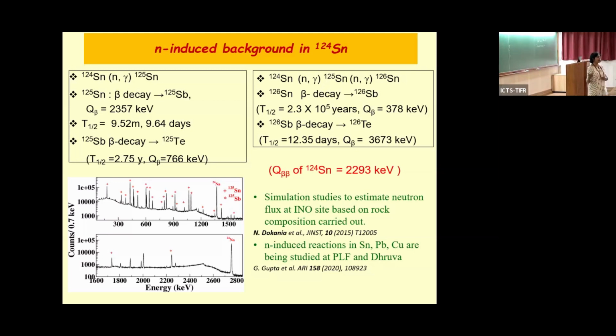So like when we bought the Roman lead, we had to make sure that it came by the sea and not by flight, because otherwise it would have created more activity. And in fact, all the germanium for experiments which has gone from Russia is always surface transported. But what is more worrisome is if you have a high neutron flux, it will have a sequential reaction, right? Because 124 can go to 125 and 125 can go to 126.